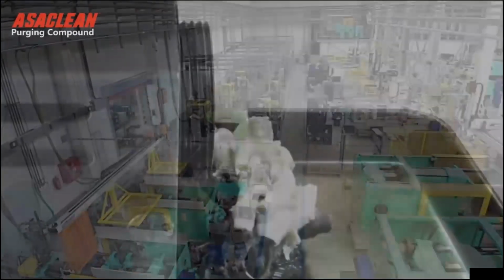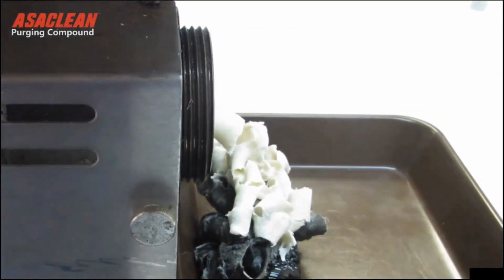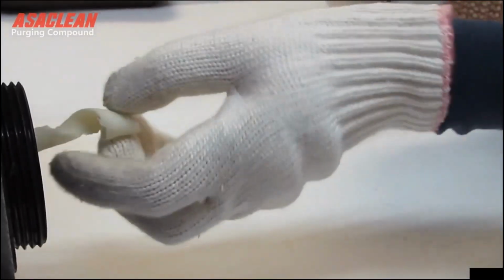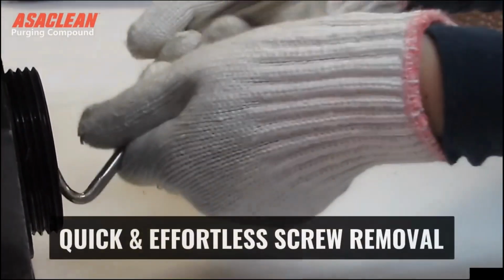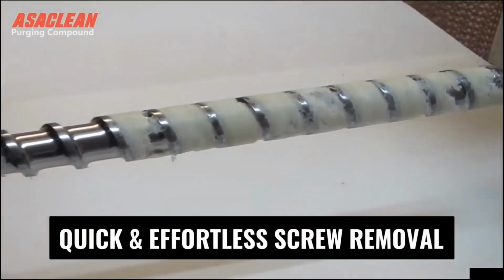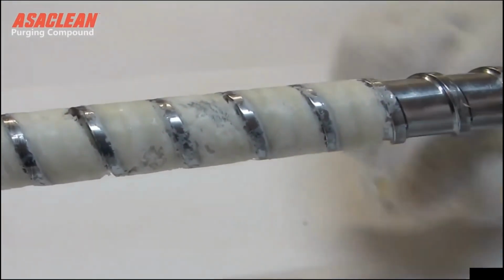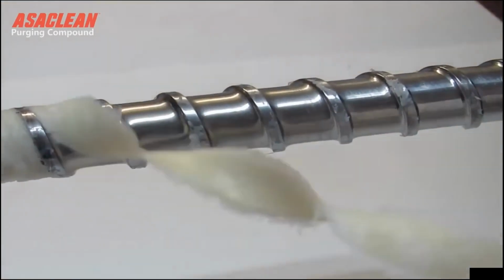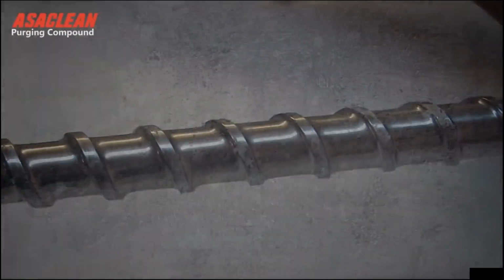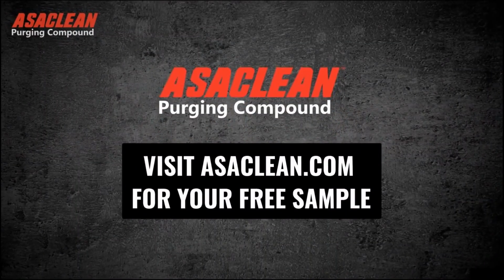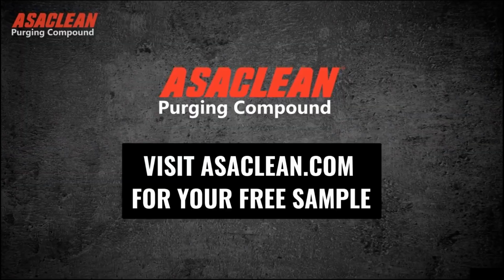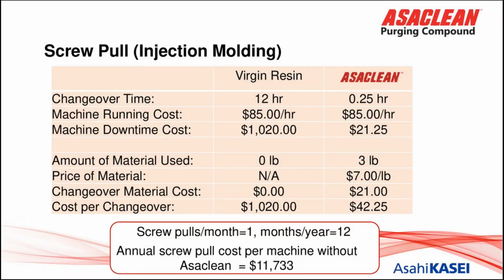Now what we're going to see is that same machine after being purged with Asaclean. The first thing you're going to notice is the extrudate is nice and clean, meaning we got all that black ABS out of there. But this is the real magic, guys. The screw becomes very, very easy to pull out. And as you can see, the Asaclean purge compound will peel off the flights and the root of the screw in one ribbon like a banana. Your screw and barrel is going to look like it just came out of the box. I can't tell you how many screw pulls we save annually with this particular product. I've used this personally on equipment. I've used this personally on 6-inch screws that were 24 feet long, and we had the same type of results.